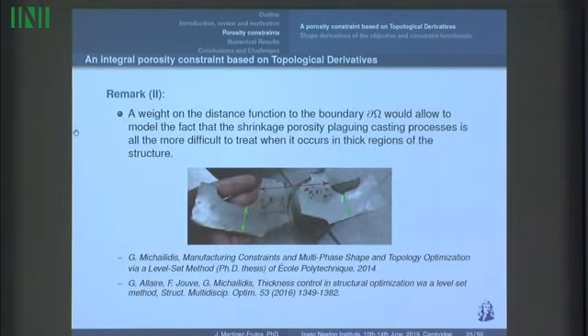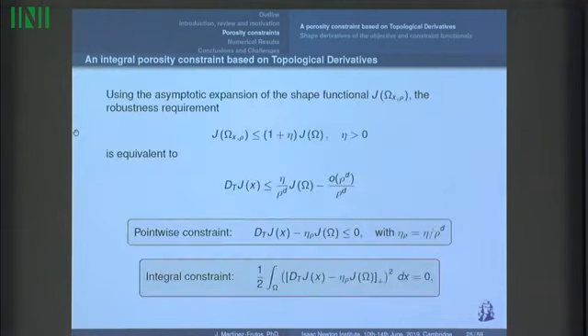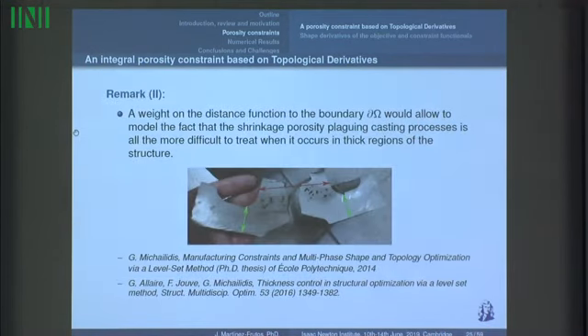The second remark is related to a possibility of improvement, which is related to shrinkage defects. So in this constraint, we can also include a weight on the distance function to the boundary. Why? Because shrinkage cavities appear in hot spots of the structures and are even more probable to appear in parts with large thickness. So we can extend this previous work to incorporate this weight on the distance function to the boundary in the formulation.